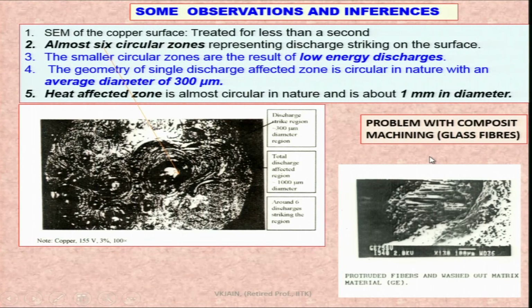So, the one which has the lower melting point will get melted out first, and the others may get melted out or vaporized later on. That is what we have seen in many cases like this. When Mr. Tandon, if I remember correctly, conducted his experiment, this problem was clearly seen. These are the glass fibers, and this is the base material that has melted out, because it has the lower melting temperature, while glass fibers had a much higher melting temperature. So, one has to be very careful while machining composite materials.